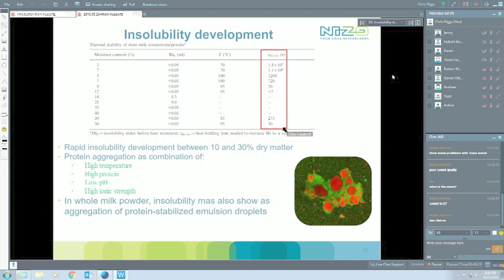Of course, your temperature is still reasonably high at that point because it has concentrated quite far, and your pH has dropped. That combination will determine a lot of your insolubility development, and that's related to the temperatures you're using in your dryer, but also the solids content that you go onto the dryer with. Because in those initial stages when the powder particle is in the dryer, temperature will be a bit higher. And if it's very concentrated already at that point, then you can get insolubility happening there as well.